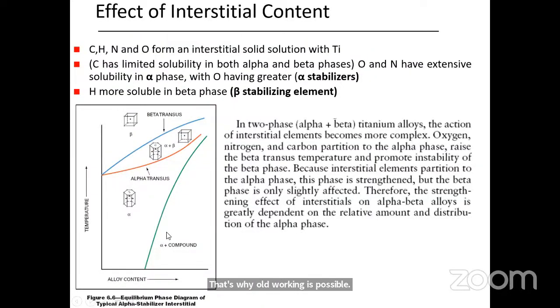If you see this phase diagram, when you add alpha stabilizers, it raises the beta transition temperature. For example, oxygen, nitrogen and carbon are alpha stabilizers. They mainly raise the beta transition temperature. Interstitial elements like oxygen and nitrogen have extensive solubility in the alpha phase, with oxygen having the greater solubility. Hydrogen is more soluble in the beta phase than the alpha phase.